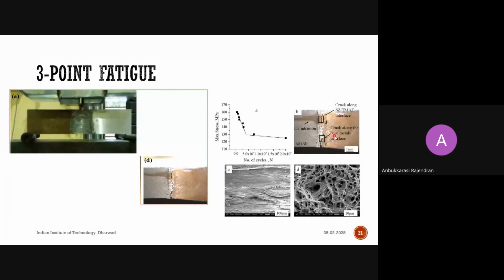After fracture, for each sample, as I said, we wanted to do the crack propagation analysis. This region went to brittle fracture. This region underwent ductile fracture. For the same sample, if you can recall the EPMA mapping, there was a fine intermetallic layer at the interface. As it failed along that intermetallic, it underwent brittle fracture. When the propagation went through copper, it is completely ductile fracture. So the ductile fracture we could identify in the region where the propagation happened along the copper.